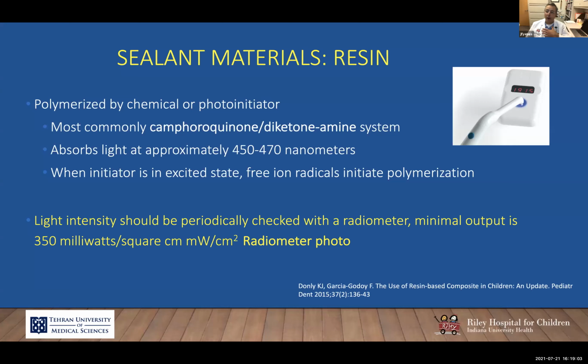Interesting, a few years ago, one of our residents did a study looking at the intensity of the light every 6 months. And you are not going to believe it, but very often the light curing lights lost a little bit of the intensity with time. We found that after a year and a half, that light is not providing the intensity you need to cure the sealant. So the light intensity should be periodically checked with the device, and the minimal output is 350 milliwatts per square centimeter. That means that is the minimal intensity that you need for the light cure in order to polymerize the sealant.